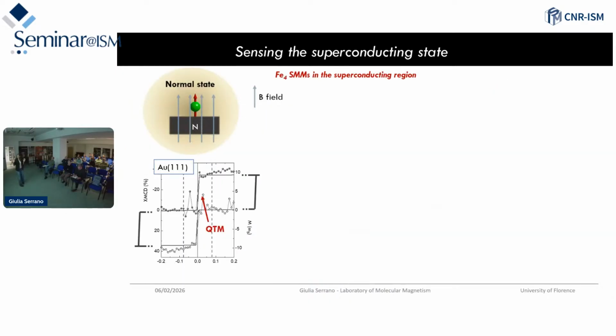Then what we expect, for example, if we probe this on gold 111, is that the magnetization of the molecule, this is a zoom close to zero of the hysteresis, stays flat, roughly constant, until field zero, and then starts to do the resonant tunneling of the magnetization.